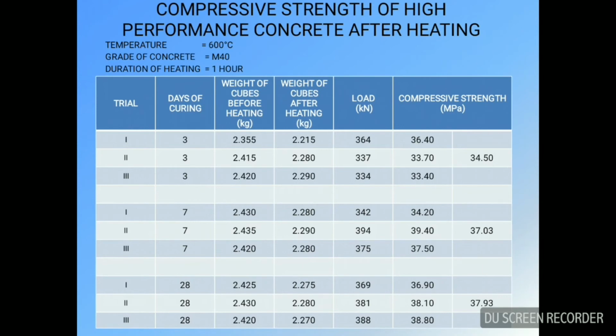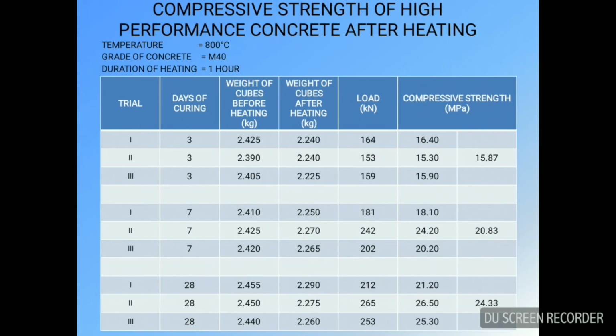Now the strength came around to be 37.93, which is about 70% of the strength that we had initially, our target strength. Lastly, we did M40 at 800 degrees Celsius for 1 hour of heating, and this shows a major drawback, as it did not provide even 40% of our initial target strength, at about 24.33 megapascal.